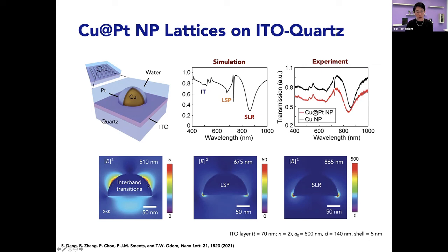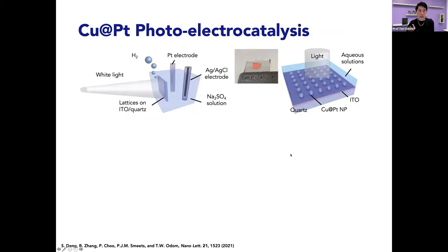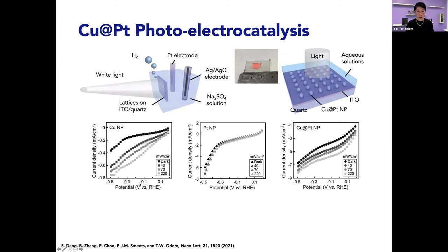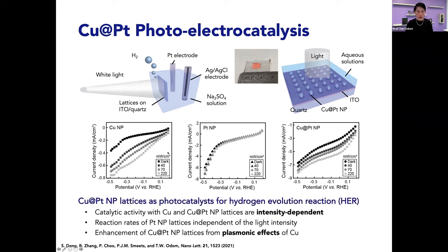So these are at different wavelength ranges, longer wavelength for the SLR, redder for the LSP, and these interband transitions are green wavelengths, but you can see that the intensities are orders of magnitude different. So then we tested this photo-electrocatalysis under white light. This is the electrochemistry setup in a neutral pH. And you can see if we compare the current density versus potential for copper nanoparticles, platinum, and then the ones with the core shell particles, that if you change the intensity of the white light, that the copper nanoparticles and